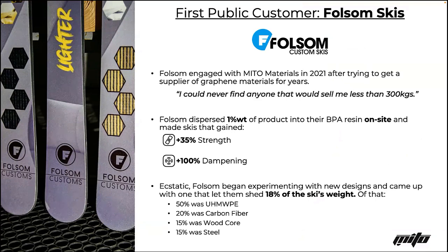But with this product, they went back to the drawing board, and what they found is that they were able to decrease the weight of the ski by 18%. So they were able to save ultra-high molecular weight polyethylene, carbon fiber, wood, and steel with just 10 grams of product. So they were able to make an ultralight ski that is actually worth something. It doesn't chatter. You can still control it. It's a really nice ride.